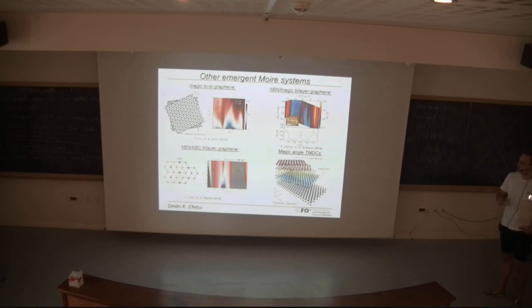For example, in a recent study by the Harvard group, they have shown that you can do the same trick by twisting bilayers on bilayers. So instead of twisting a single layer on a single layer, you twist 2 bilayers on top of one another, and you get a very similar phenomenology. You also observe correlated states, and people think that they also observe superconductivity. So this magic angle trick also works for bilayers. It should work for trilayers. The top is an AB stacked bilayer graphene, and the bottom layer is AB stacked bilayer graphene. You could do this with trilayer stacked on trilayer, 4 layers on 4 layers, I don't know.